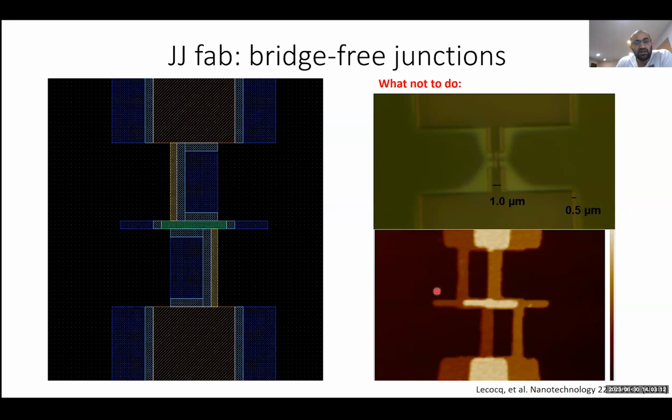Now, this is a problem that can be fixed, but it's something that you have to be aware of. And really, one way to fix it is to make this wide region a lot thinner in order to reduce the total nearby exposure to your close-by junction area.